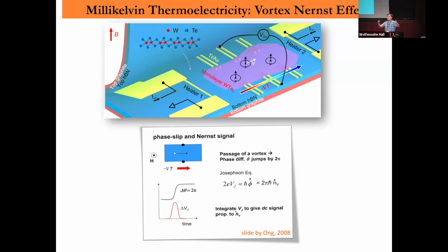It doesn't carry entropy. But if you have a vortex there, in the core of the vortex, there are normal electrons which carry entropy. So what happens if you have a temperature gradient, then this normal electron will diffuse, will follow the temperature gradient. It'll move because of the presence of the entropy and temperature gradient. So this temperature gradient will drive this vortex this way.